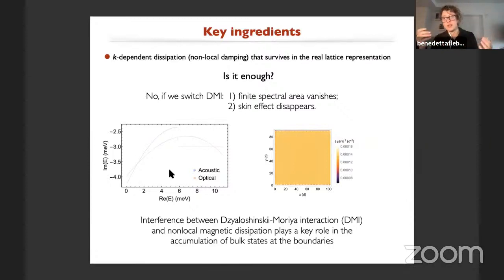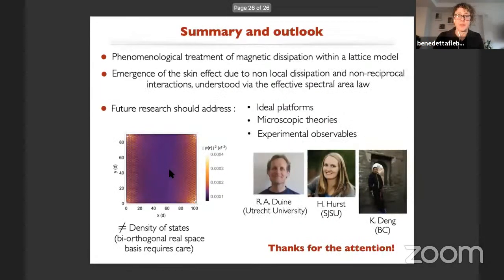But more physically, to observe the skin effect, we need some interference between an interaction that is by definition non-reciprocal, such as the Dzyaloshinskii-Moriya interaction, and some non-local magnetic dissipations. So it's really the interference, at least in our model, between the two that is playing a very key role in accumulating the bulk states at the boundaries.